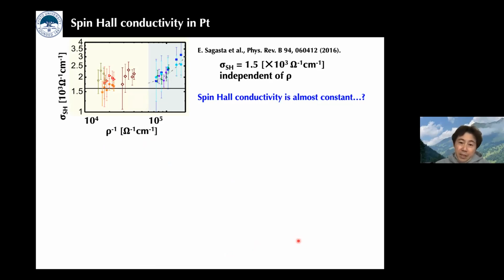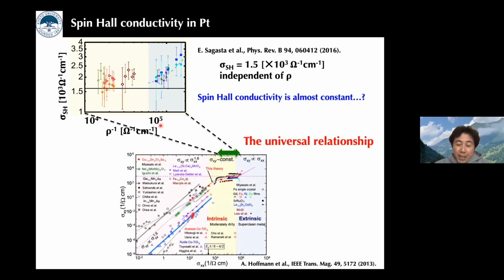Of course, the spin Hall conductivity as a function of the resistivity was investigated by some people, and this is the result. But according to their manuscript, they claim that the spin Hall conductivity is almost constant with respect to the resistivity of the film. But if we replot this result in this famous universal relationship between the normal conductivity and the spin Hall or anomalous Hall conductivity, we can understand the following. The Spanish group controlled the conductivity of their platinum film within the intrinsic regime, but the highly conductive, I mean low resistive, regime. In our experimental scheme, our platinum is also within the intrinsic regime, but at the opposite border of theirs.